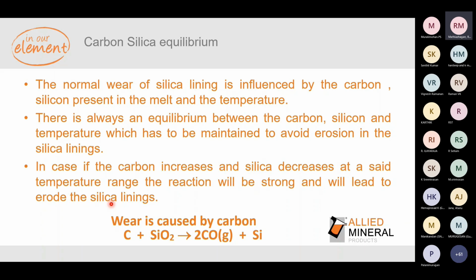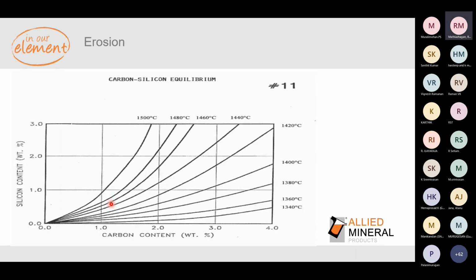When it comes to erosion, carbon silicon equilibrium plays a major role at a set temperature. In case the carbon increases in the liquid metal and the silicon percentage decreases at a set temperature range, the reaction towards the silica lining is going to be strong, and the carbon is going to pull out the silica from the main working lining and erode it. So this carbon silicon equilibrium is a graph which we normally show to our customers, about the equilibrium we have to maintain at a set temperature to avoid any kind of attack over the main silica lining and to control the erosion pattern.